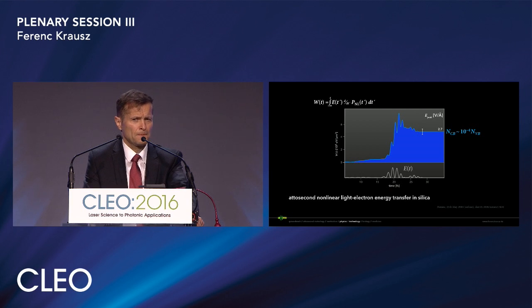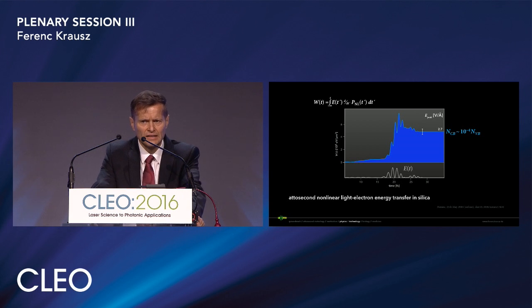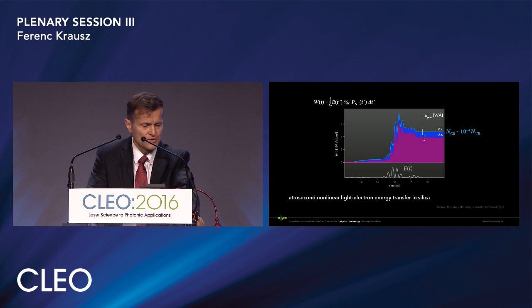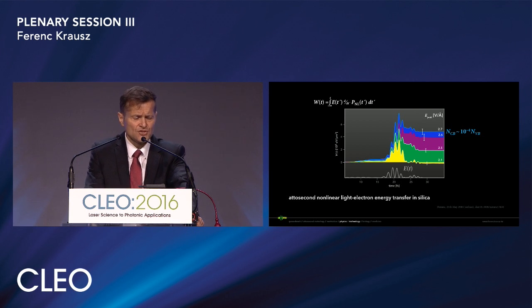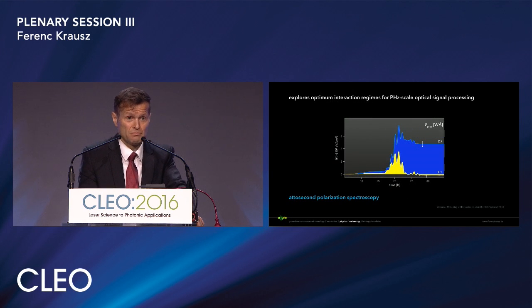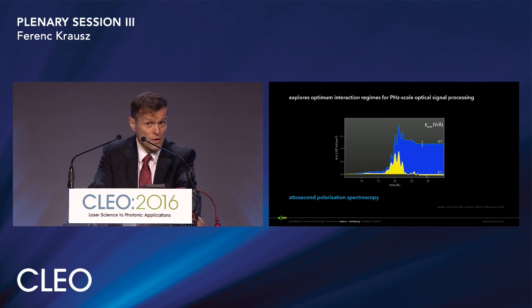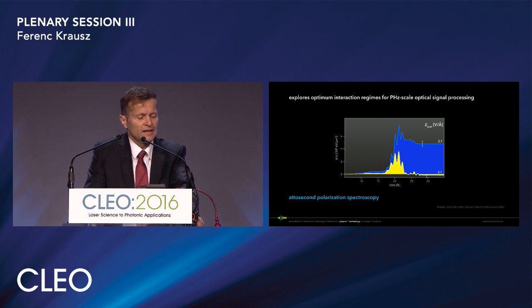for scaling electronic signal processing towards terahertz and possibly even petahertz frequencies, where even a small amount of this population generated upon each switching cycle would rapidly accumulate upon subsequent switching cycles and lead to intolerable dissipation. Fortunately, a moderate decrease of the electric field strength by as little as 25% decreases the irreversible energy transfer dramatically, actually below our current detection limit, whilst leaving the reversible part of the transferred energy that is useful for signal processing nearly unchanged.